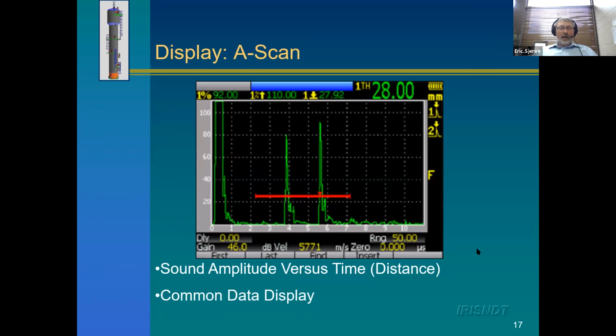Now, the main display in ultrasonic testing is an A scan, and that's just that the y-axis has ultrasonic sound pressure. So that's just the size of the signal. And the scale on the x-axis is time, or because we know the velocity of the wave, it's distance into the material. So that's the main display you're going to see. And typically, the bigger signals you get are from bigger defects. Smaller signals are from smaller defects. So that's typically how this inspection is done or interpreted.